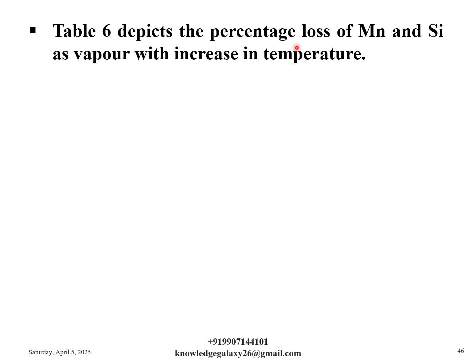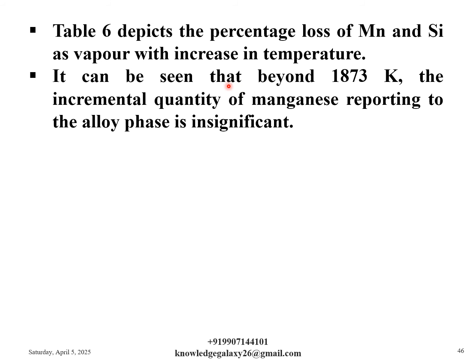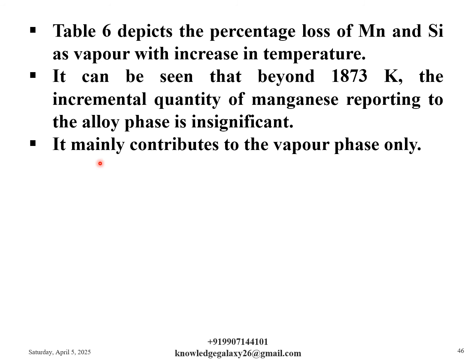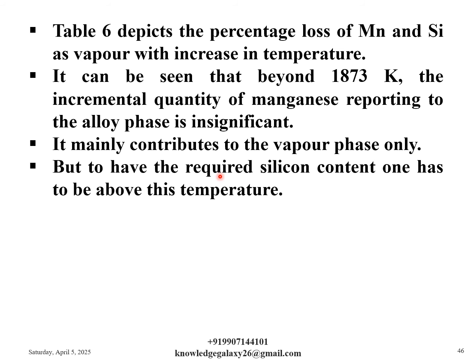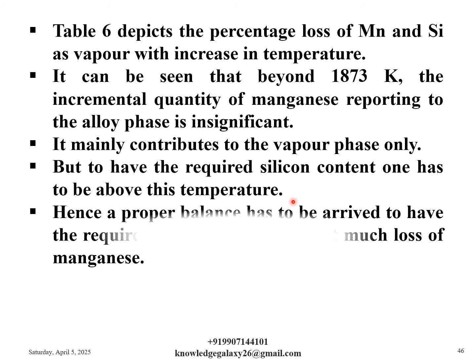Table 6 depicts the percentage loss of manganese and silicon as vapor with increase in temperature. It can be seen that beyond 1873 Kelvin, the incremental quantity of manganese reporting to the alloy phase is insignificant. It mainly contributes to the vapor phase only. But to have the required silicon content, one has to be above this temperature. Hence, a proper balance has to be arrived at to have the required silicon content without much loss of manganese.